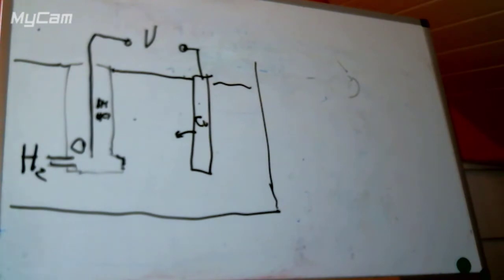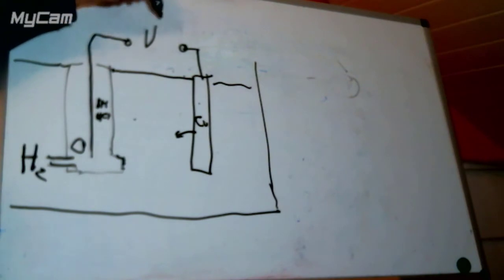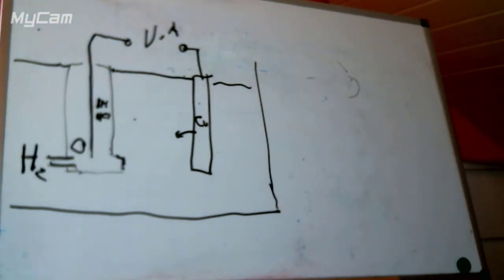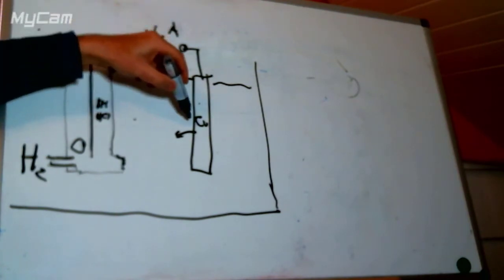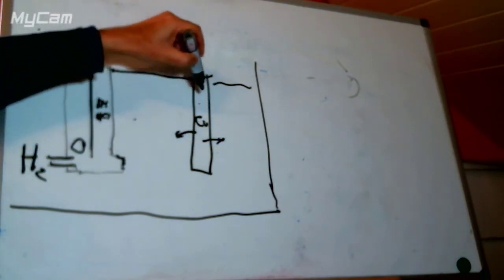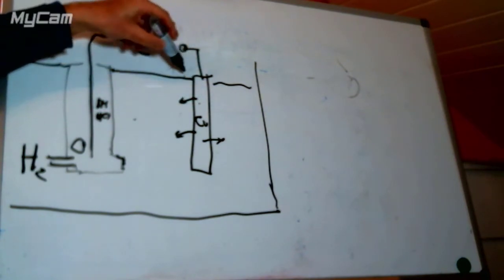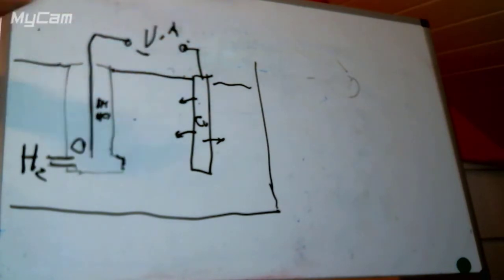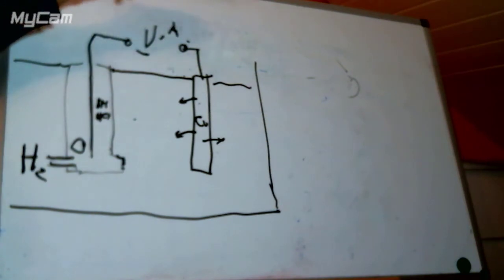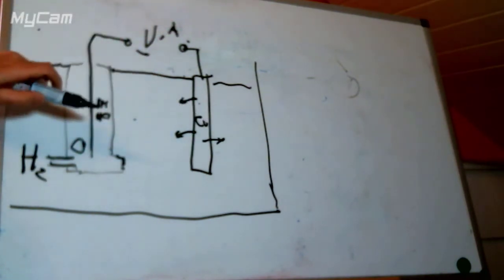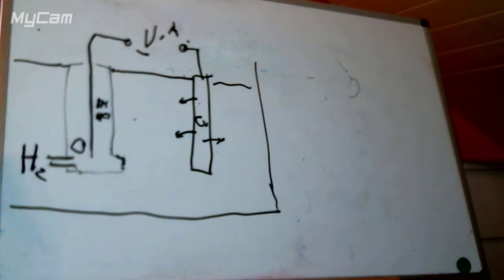Now we come to the interesting part. We can get two things out of a cell. We can get voltage and we can get current, and we could measure both or either. The voltage is measuring one thing: the voltage is a measure of how strongly the copper is dissolving. The stronger the copper dissolves, the more negative this voltage. The more positive this voltage, the more the copper from solution is trying to get back onto our copper electrode. So we can measure that.